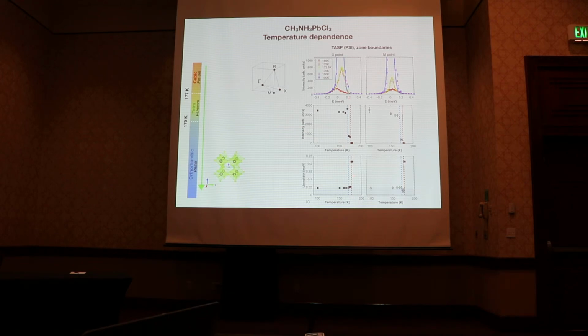And what is also striking is that the energy line width of this scattering remains resolution limited for all temperatures. So what we can see at high temperature here is an energy line width that corresponds to the instrumental resolution that is extracted from incoherent signal of a vanadium standard. And at low temperature, it drops to the Bragg resolution of the instrument, and this is associated to the delta function in energy and momentum.